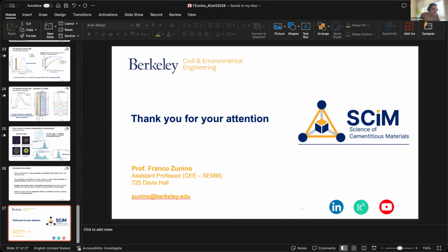And then there is a last question that says, thanks for answering my question. Why doesn't crystallite size apply in this case? Because I don't think that there are crystallites. I don't think that you have domains that are large enough to meaningfully call it a crystallite. So in the case of CSH, I think that we have crystallites. A crystallite of CSH is roughly 5 to 10 nanometers. So that's the ordered domain or the size of the nanofoil, as we call it. You don't even have that for what we have seen so far in metakaolin. It is more disordered than that.